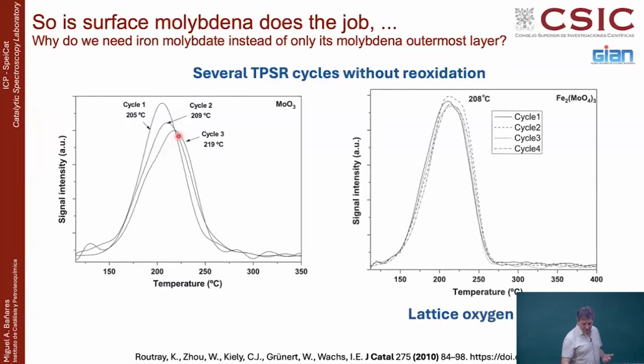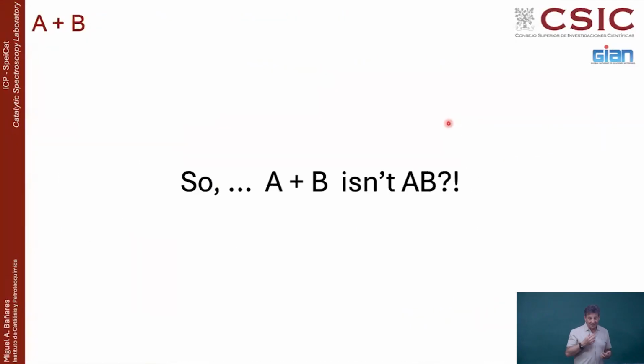If you do that on iron molybdate, you put methanol, you make formaldehyde. Another cycle, formaldehyde. Another cycle, formaldehyde. I can do whatever you want. So why? Because you're also getting the lattice mobility provided by the iron molybdate, so that you get also a more efficient surface. So even when the surface is not like the bulk, the bulk does have an effect on it, and this is very important. And these kinds of experiments show you the importance of the lattice mobility in these kinds of materials.